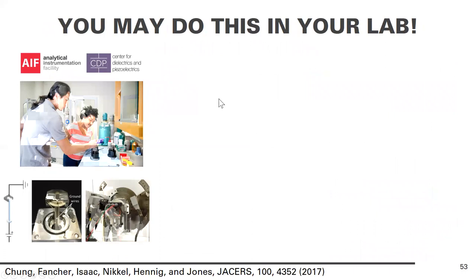I do have one more thing. You may be able to do some of this in your lab. In a project sponsored by the Center for Dielectrics and Piezoelectrics and carried out in our analytical instrumentation facility here at NC State, we developed an in situ loading cell where we can apply electric fields to thin films and to polycrystalline samples at room temperature and also at elevated temperatures. And so anyone watching this call actually has access to do experiments using this type of setup in this open access facility.